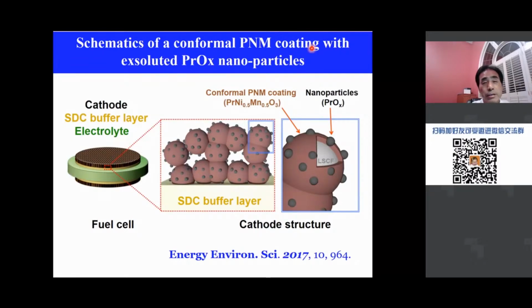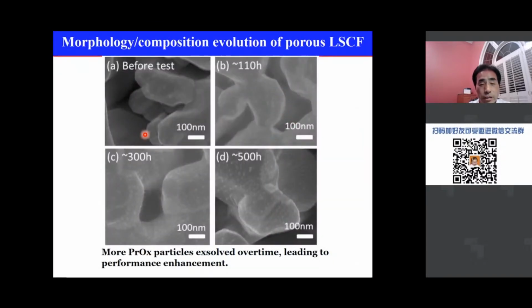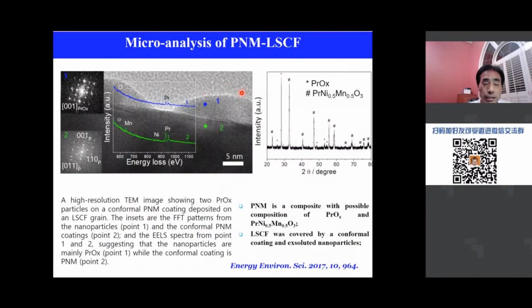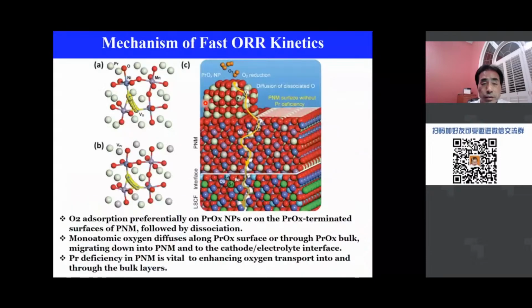Yeah. As a specific example here, we have put a PNM coating on LSCF, and then by controlling the process and condition, you can also have exsolved nanoparticles of praseodymium oxide, and that creates a uniform coating plus some nanoparticles on the surface. And this is what it looks like under SEM. You can see the nanoparticles after different times of annealing. Then by carefully analyzing the chemistry and the composition of the material, we identified it is actually praseodymium oxide nanoparticles on a PNM coating. So this is a schematic of the model for that surface structure created. And then we use DFT calculation to try to explain why this coating can increase not only the catalytic activity, but also the stability. The praseodymium oxide is very active for adsorption of oxygen and oxygen reduction.